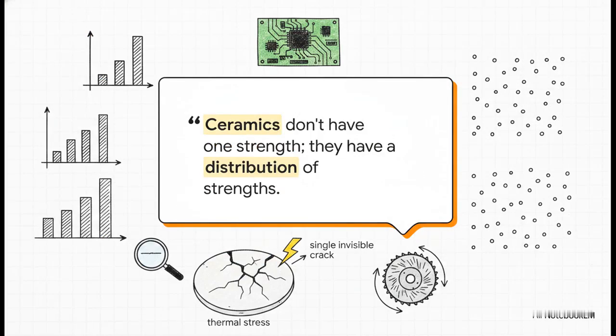Which brings up a really fascinating engineering concept, perfectly captured by this quote. Ceramics don't have one strength. They have a distribution of strengths. Engineers call this Weibull reliability. Because aluminum nitride is so brittle, its failure is entirely dictated by microscopic flaws. Literally, a single invisible crack introduced while diamond grinding the edges can cause a high-voltage substrate to catastrophically shatter under thermal stress. So you aren't just buying the material, you're paying for the absolute perfection of its processing.